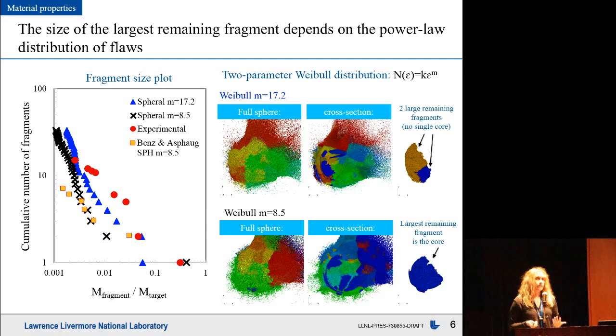So we're pleased to find that our spheral results match the experimental trend using the experimentally measured K and M parameters by Nakamura, and did a better job than the arbitrarily measured and widely used parameter M equals 8.5, meaning spheral is sensitive to the material parameter selected, as it should be, as we had hoped, and can do a really good job physically representing what is observed experimentally when given well-analyzed initial conditions.